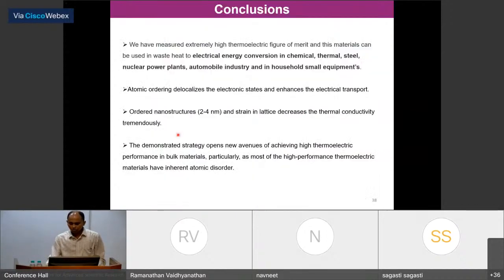With that, I conclude. Today I showed fundamental discovery in thermoelectrics. Generally I want to summarize in one sentence here, because the field moves towards disordering, because till now people proposed that disordering can increase the thermoelectric figure of merit by decreasing the thermal conductivity, because the entropy of the system increases, and that's why we see low thermal conductivity and high ZT.